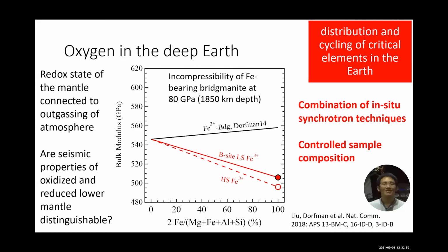So yes, the plot that I showed, which I can pull up the slide and show again, is from a fixed pressure, actually. It's at 80 GPa, so that I can avoid any worrying about the spin transition. So this is at a fixed pressure of 80 gigapascals. We are above the spin transition, and this was what we found in this condition. But certainly while the spin transition is going on, I know that we have softening that we need to worry about, and so that's why I picked this particular pressure to compare.